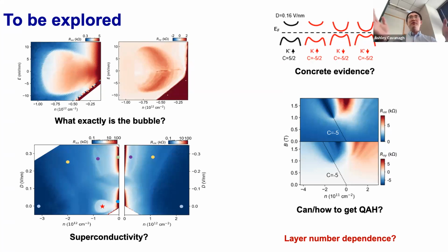You are probably thinking, if you don't apply any bias voltage, what does that photocurrent mean? The reality is you have a huge beam spot. In our case, the beam spot is on the order of 1 millimeter, with a tiny little sample there, and the sample could very likely have asymmetry between the source and drain. I have never seen any 2D material sample where you shine light without bias and don't get current. Usually you always get some current.